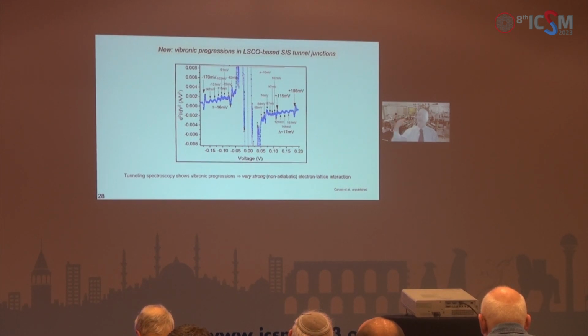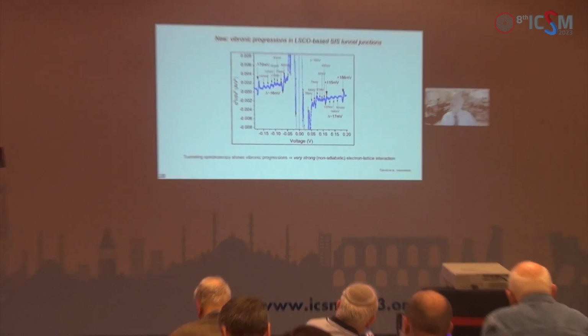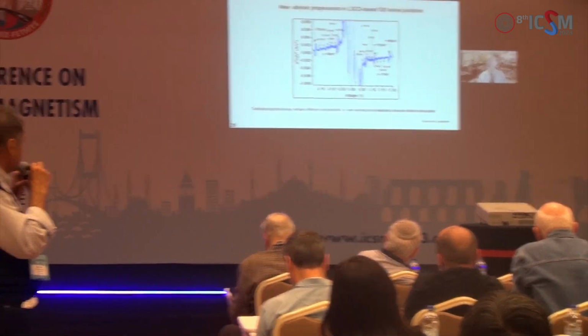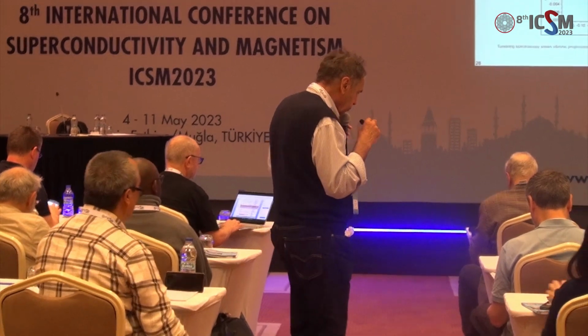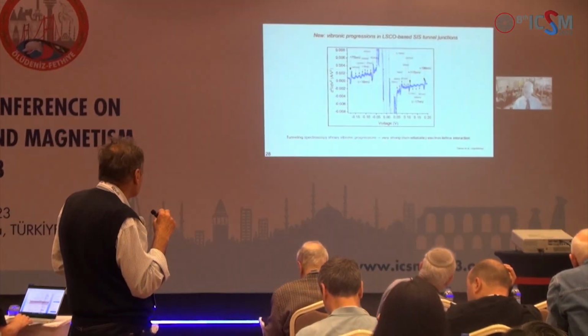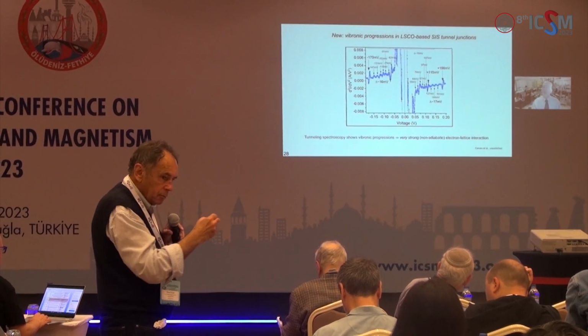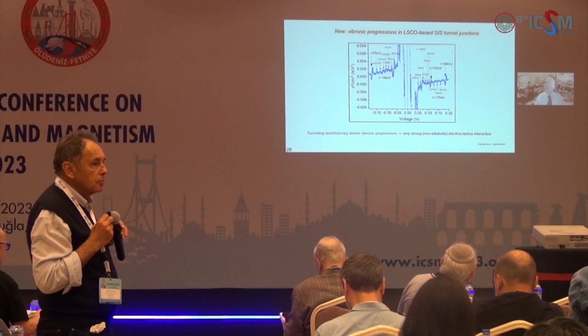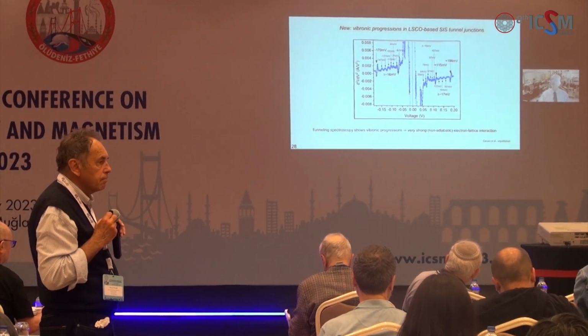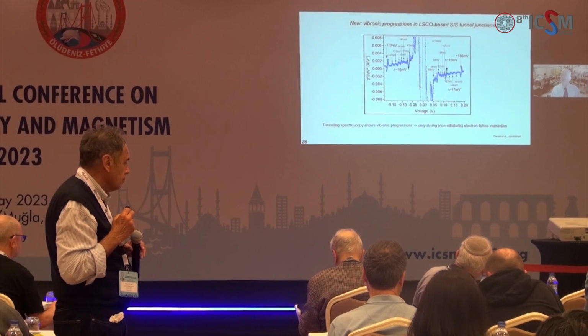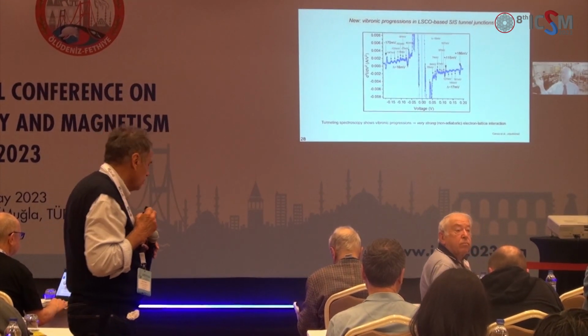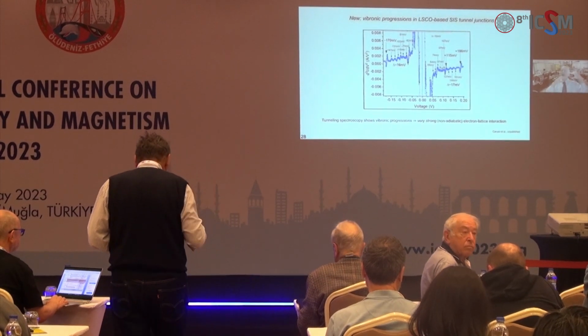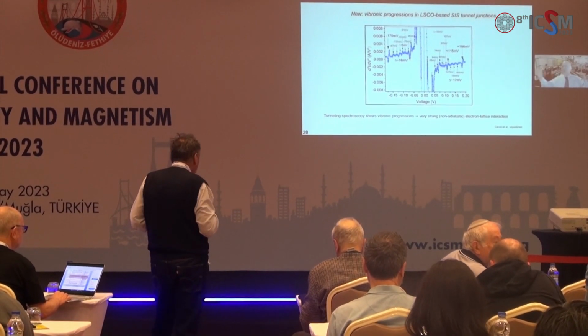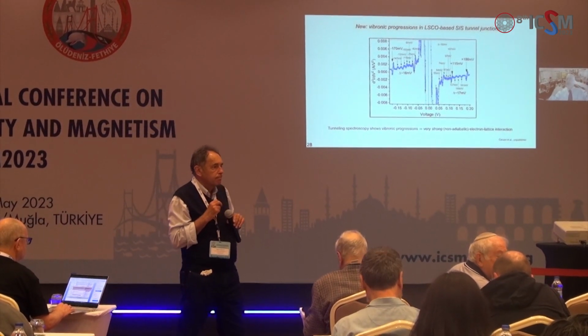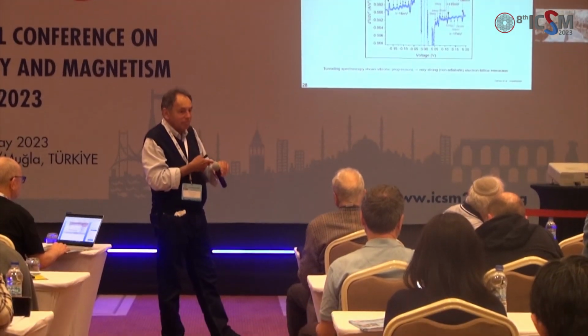But you're right, there is much to be learned from the doping dependence, which I almost completely skipped here except for the superfluid density. To make it short, it looks like the best fits are obtained when you use something like a two-component model, where one component is strange, meaning linear rho versus T and rho versus B, and the other one is T-squared dependent, more like a Fermi liquid. And what happens when you increase the doping is that the relative contribution of one is going down and the other one is going up.